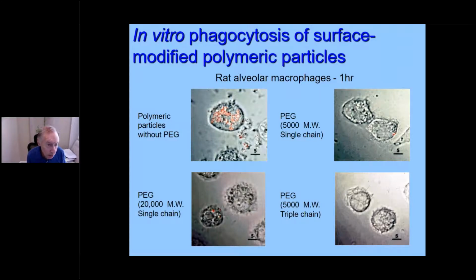and saw how long they would last when we incubate them with macrophages. If you don't have the PEG, you can see in an hour, look at all the little orange dots in the cell. But when you do put the PEG, like a 5,000 molecular weight one or a 20,000 one, you can see that you get a lot less taken up. And then Avi Domb was a postdoc with me and then came back for a sabbatical, and he actually made conjugates with citric acid attached to these and had a triple PEG. And there you can see on the bottom right with the triple chain, there's actually no uptake.